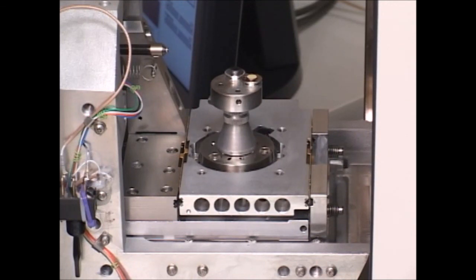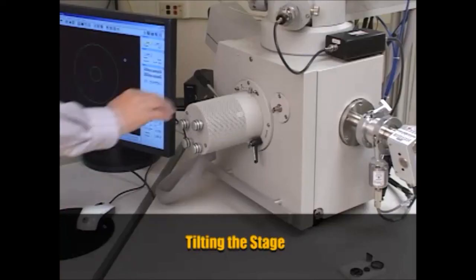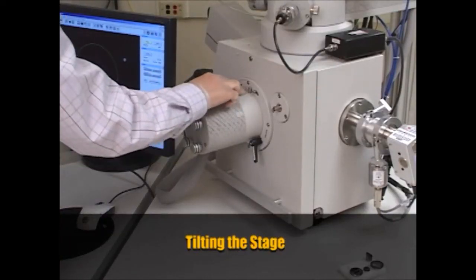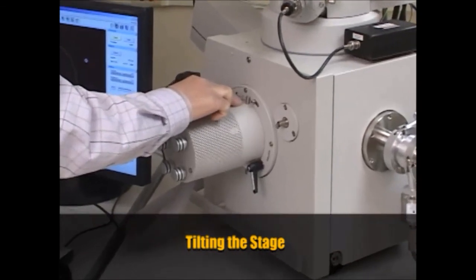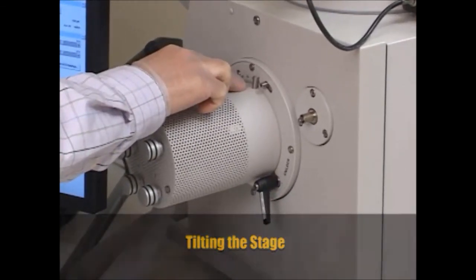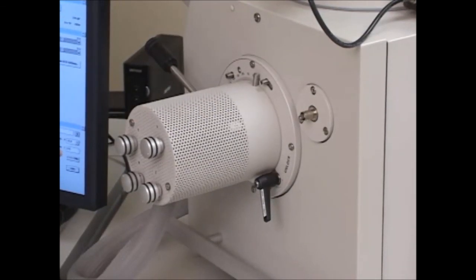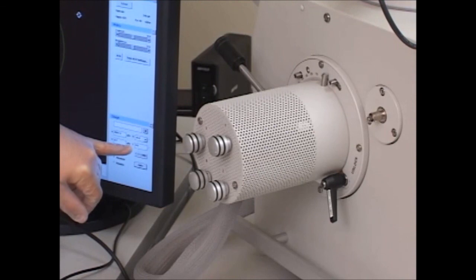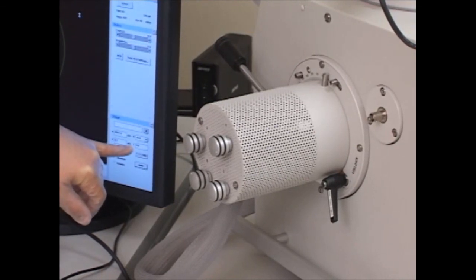One thing we didn't do that's pretty cool is rotation. So this changes the relative positions of your samples. So you can lose a sample if you're not paying attention. You can rotate it out of position. So the tilt, there's a black mark here on the top that gives you just a coarse adjustment. And right now you can see it's set at 0. You can also read the tilt from the T field here in the stage menu. And that actually reads it to 0.2 of a degree, so this is more accurate.